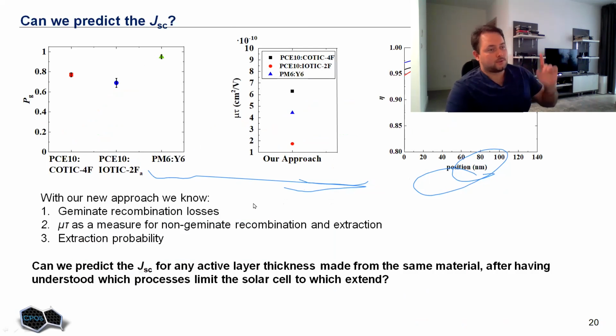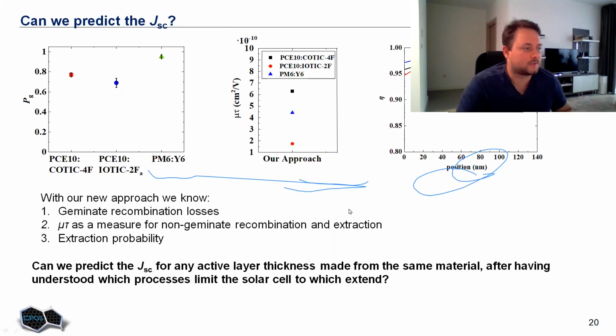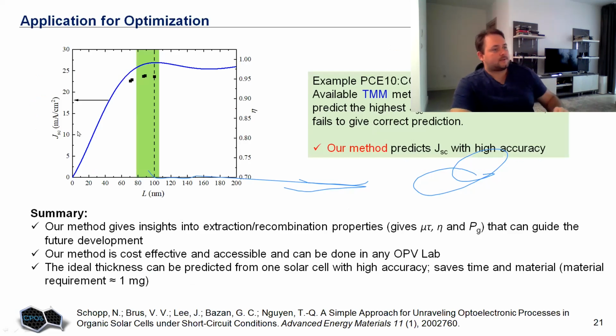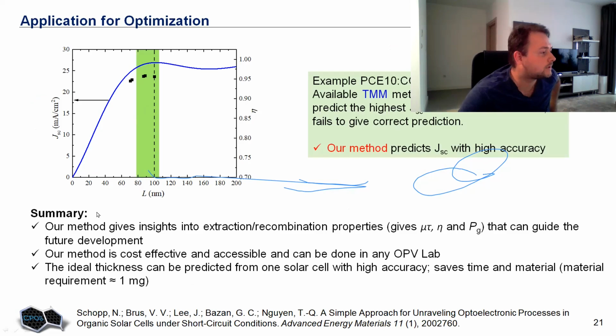Another useful application of this approach is that once we know the geminate recombination prefactor and the mu tau product, we can calculate the probability of extracting these charge carriers within the active layer. We can make predictions of the performance of our solar cells in terms of short circuit current. For instance, here we see short circuit current plotted as a function of thickness. It's not the position in the active layer, it's the thickness of the active layer. This is the simulated curve based on transfer matrix, the ideal one.